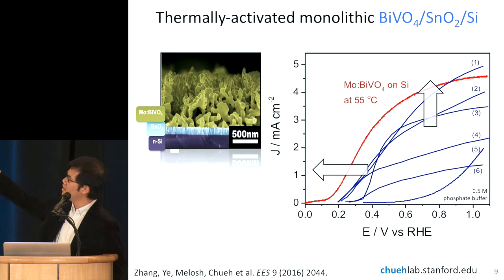On the left, you can see a cross-sectional view with bismuth vanadate on the top. We have an ohmic contact layer, tin oxide, in between, which is also transparent. And then we have n-type silicon as a substrate. The reason why we added the silicon is, if you notice on the previous slide, we were losing voltage about 2 mV/Kelvin. So it'd be good to offset that.